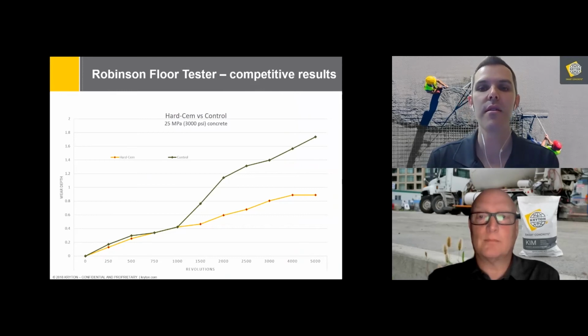Now, looking at a common example, this is using a 25 MPa or 3000 PSI concrete, very standard conventional concrete like you might use on a slab on grade or a warehouse floor. And you can see that the depth of wear using Hard-Cem was about half what was experienced just using the plain concrete. So a very significant increase in the abrasion resistance and resiliency of that concrete.